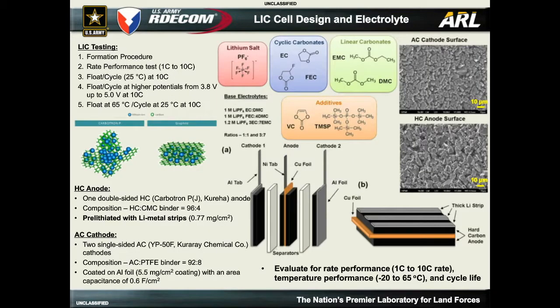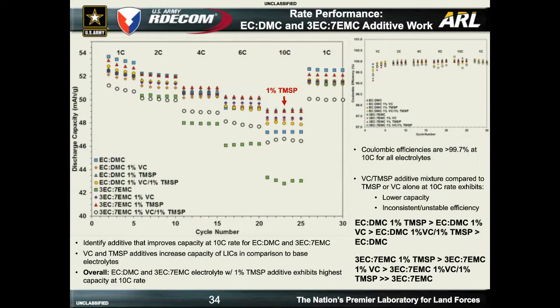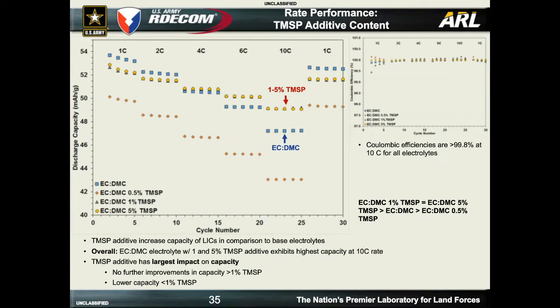And then I'll talk a little bit about some of the electrolyte work that we've done. We've looked at a variety of different additives for the lithium-ion capacitor. Most of our testing has been done in EC/DMC and EC/EMC, which are sort of the standard electrolytes for this. This just shows for different additives how the rate performance looks. And then the next chart here, again, based on the additive, we get different performance. In this particular case, the TMSP additive performs the best.